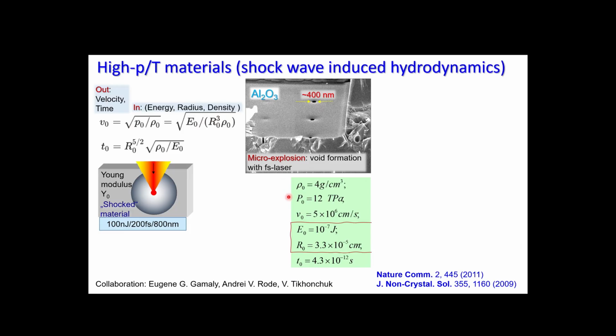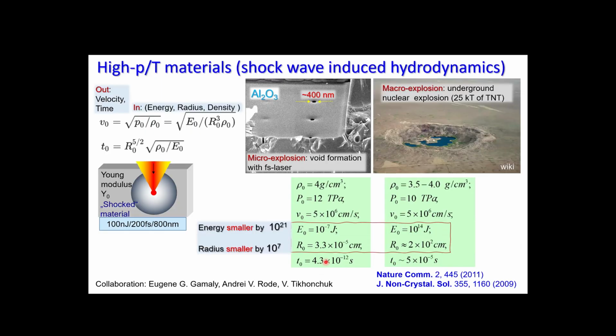The pressure which is created is huge, and then we know the shock velocity, which is around 50 kilometers per second, 5 times more than the sound velocity in sapphire. And also what we can calculate simply from this scaling is that the time when the shock emerged from the volume which is modified is actually 4 picoseconds. Without any knowledge about coupling of electrons to ions, from the strong explosion scenario, we are getting quite the right number. And quite dramatically, we can compare this with this event, which is very different.